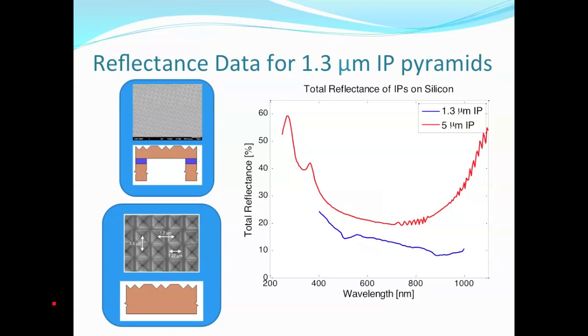Now here's some reflectance data for the 1.3 micron inverted pyramids. At this time, we don't have a textured membrane with 1.3 micron inverted pyramids, but we do have them on a thick silicon wafer. So we compare the 5 micron inverted pyramid reflectance with that on a membrane with that of the 1.3 micron inverted pyramids on a silicon wafer.